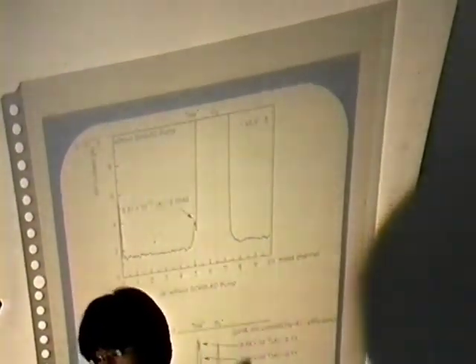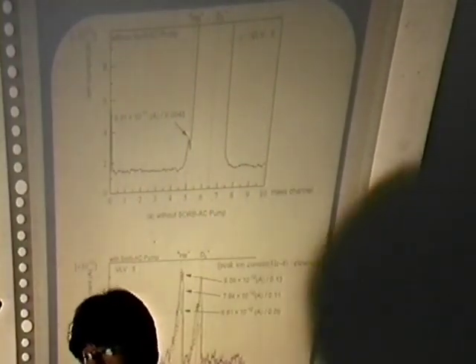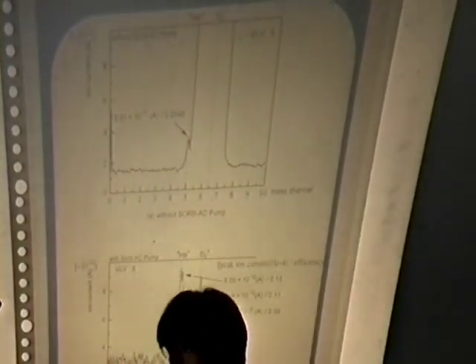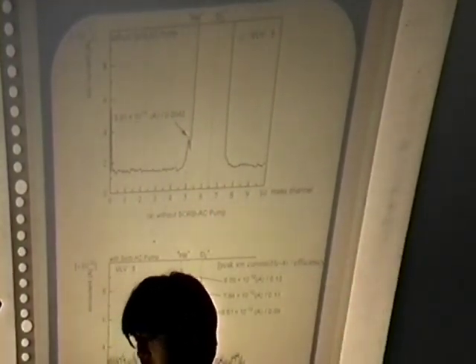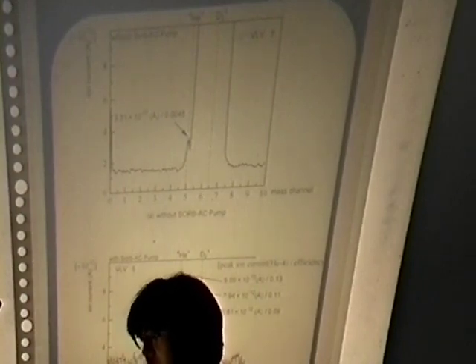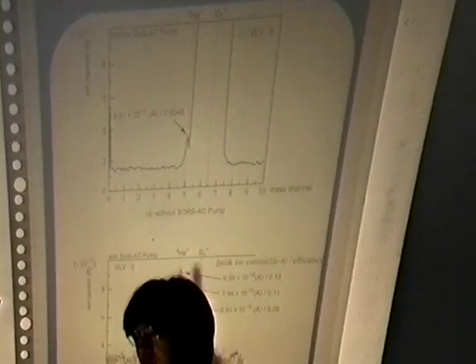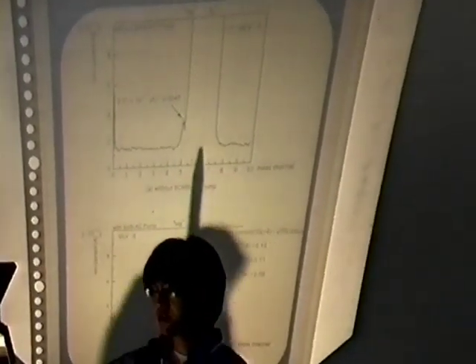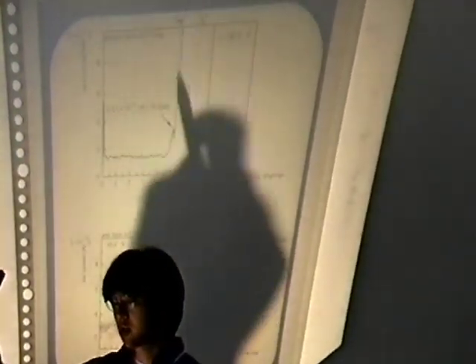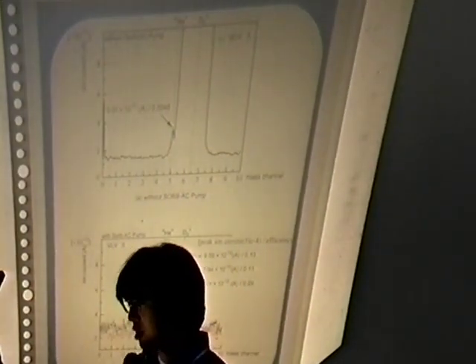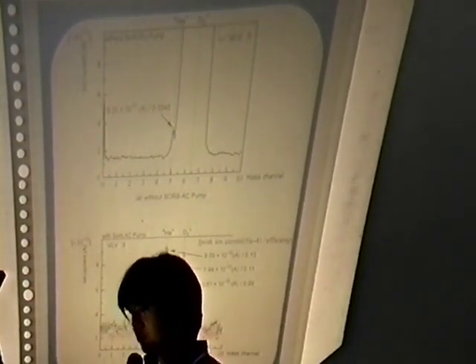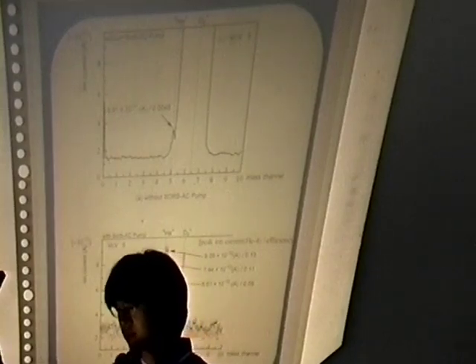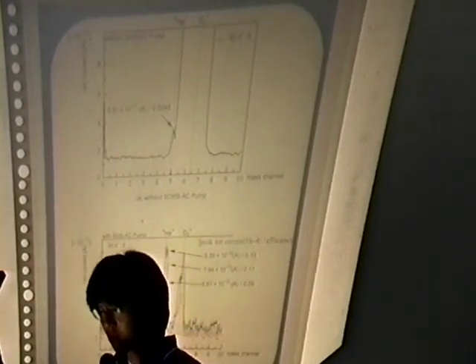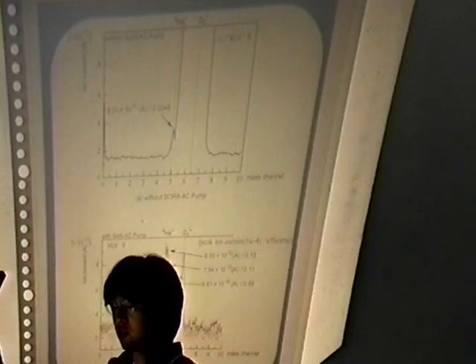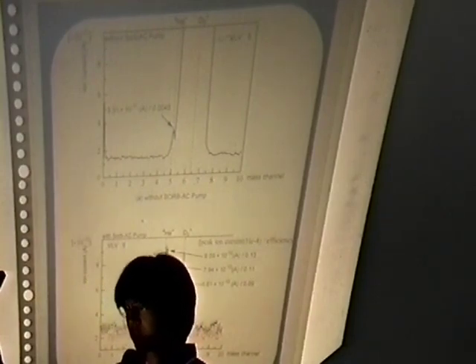I showed an example. The upper figure is a mass spectrum measured without the suction pump, and the lower is measured with the suction pump. In the upper figure, these gas peaks overlap the helium gas peaks, but by using the suction pump, these gases were removed. Then the helium-4 peak is read clearly.